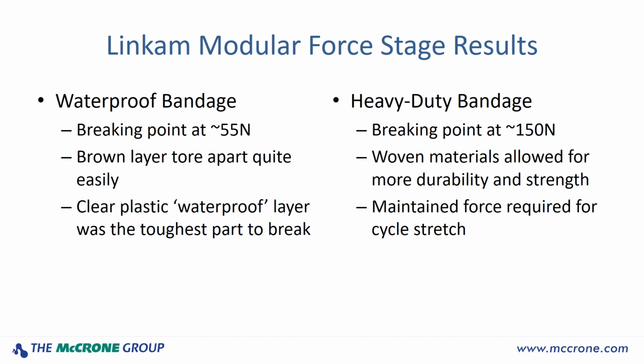For the heavy-duty bandage, it had a breaking point of roughly 150 Newton in the full stretch, and the woven materials of the bandage seemed to allow for more durability and strength throughout shorter cycle stretches and the full stretch. So we can then furthermore use this data combined with the SEM data to give a more all-around analysis of these two types of bandages.